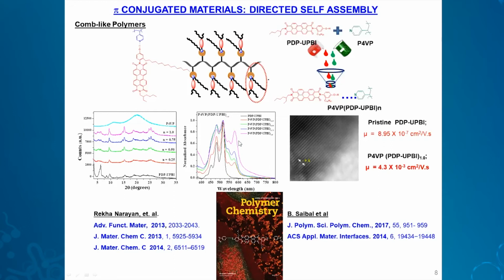So we have characterized them both in solution and in the solid form also. This is the powder XRD, and this is a TEM image. The parent materials, that is neither the small molecule nor the polymer, show any specific morphology. But once you self-assemble them, you see this beautiful lamellar structure showing, which is proof that this has been self-assembled. And also the studies show that even in solution, this self-assembly is retained, because this is the typical signature of the perylene self-assembly happening.